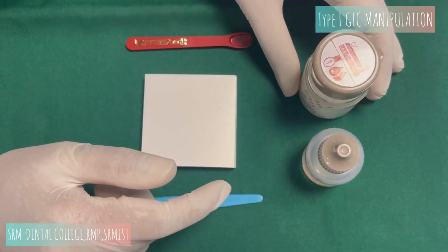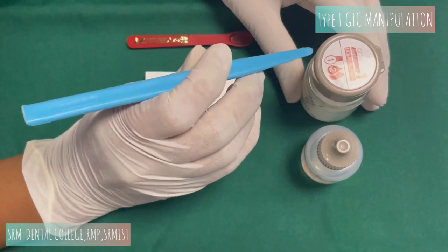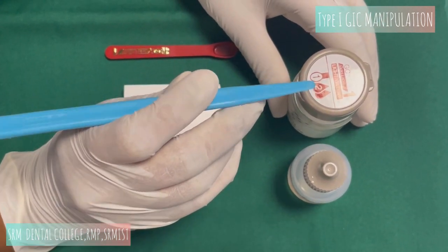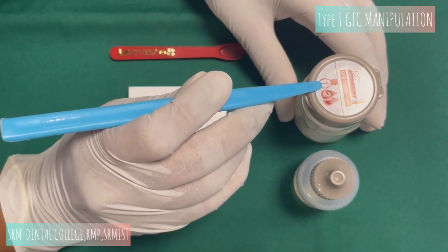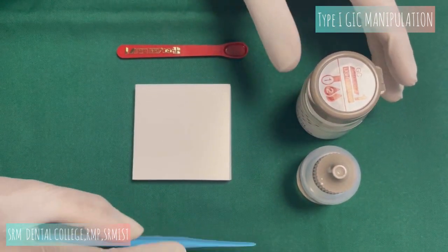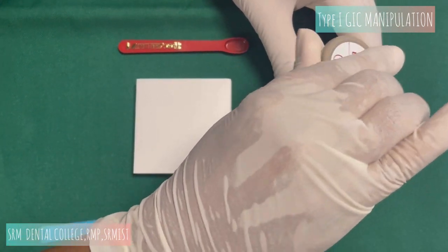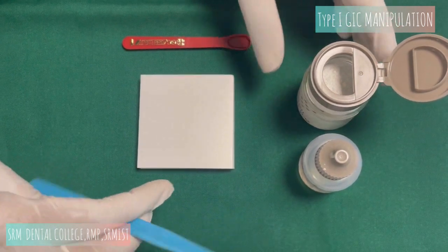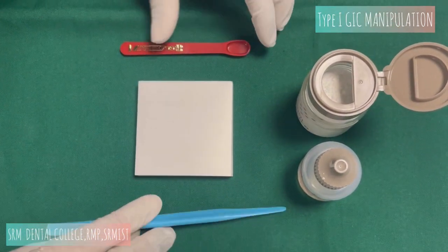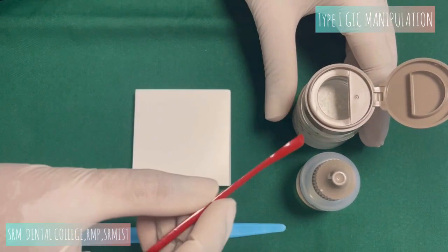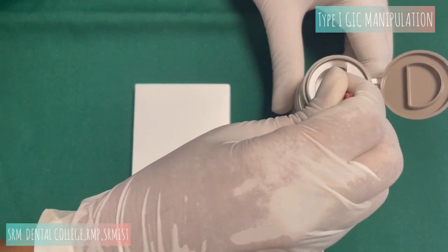That could be luting your crowns. So now as we can see, it's 1 and 2. 1 scoop of your powder with 2 drops of your liquid to get a string-like consistency so that you can use it for luting your crowns. The same armamentarium: powder, liquid, your scoop, a gauge spatula, and your paper pad.